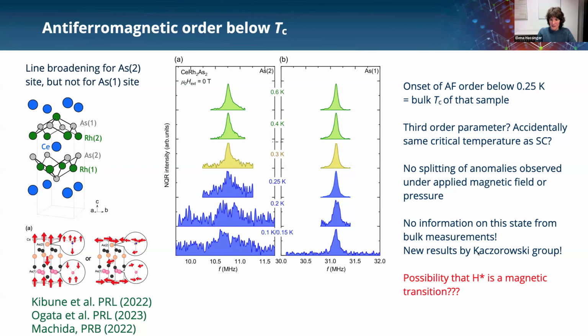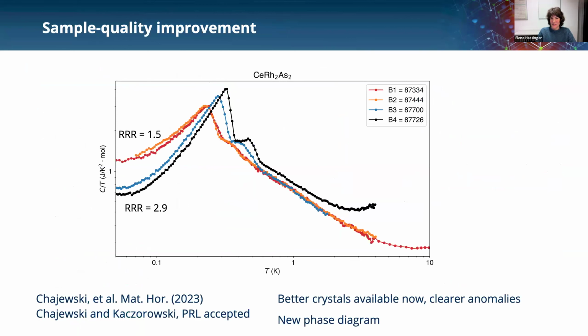And it seems that there are new results from specific heat on high quality samples by the Kaczorowski group from Poland, where they claim they have a new phase diagram. This is an accepted paper, so far only the abstract is visible. But because there's this antiferromagnetism somewhere, there was also a suggestion that the H-star transition is actually combined with a magnetic transition and not this even and odd parity. So that's also a debate.